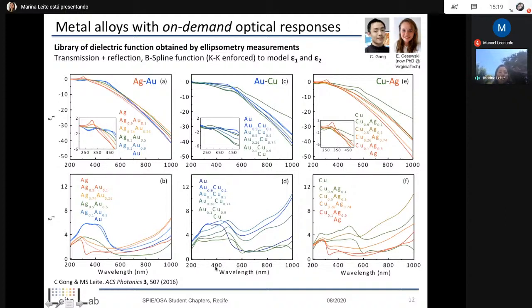Okay, but the idea here also is that, for example, for epsilon, if you look back here where I'm pointing with the mouse, this green data, 50% silver, 50% gold, turns out that this sample presented a lower epsilon 2 than pure silver in red or pure gold in blue. So this is very useful, and at the time I was really interested in this type of behavior, especially in applications where we want very little light absorption by the metal.